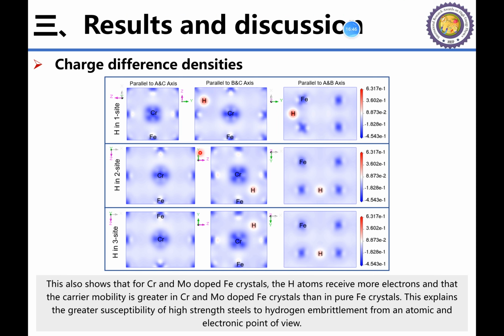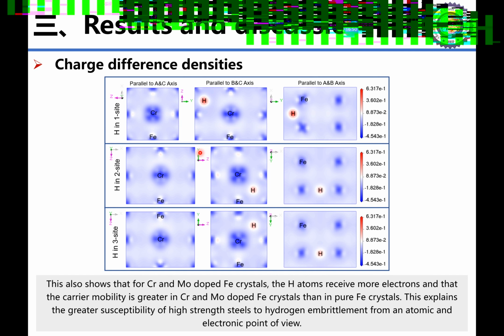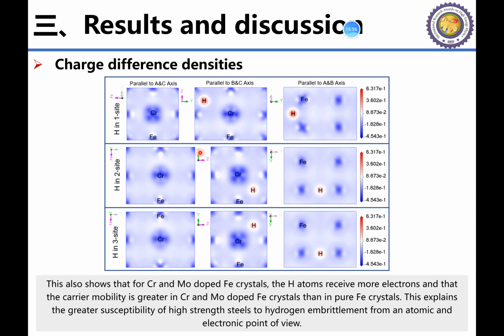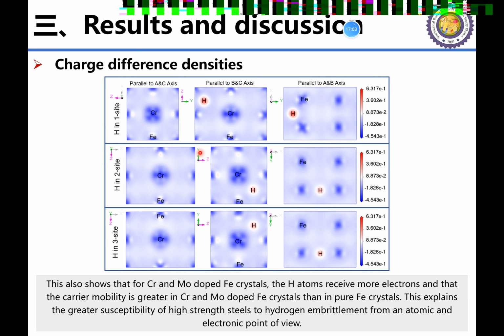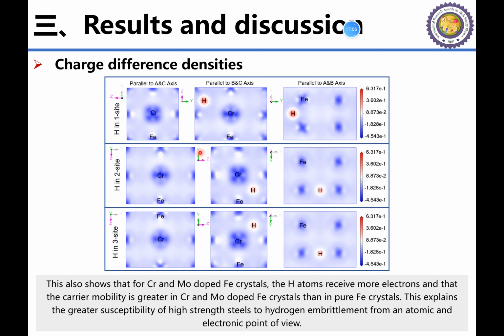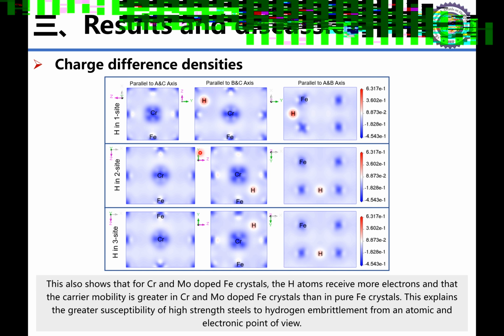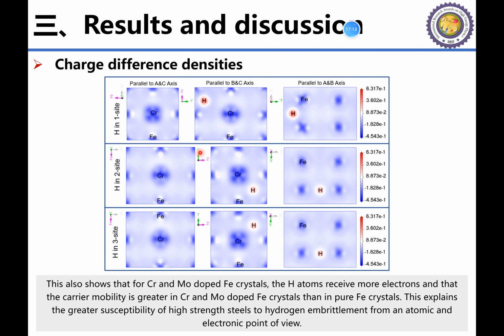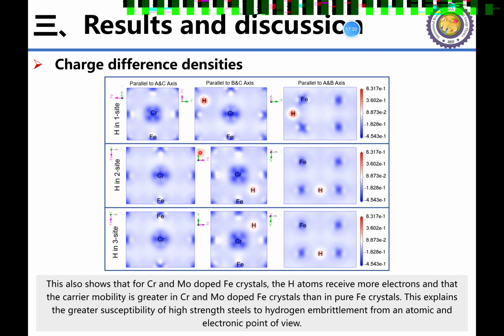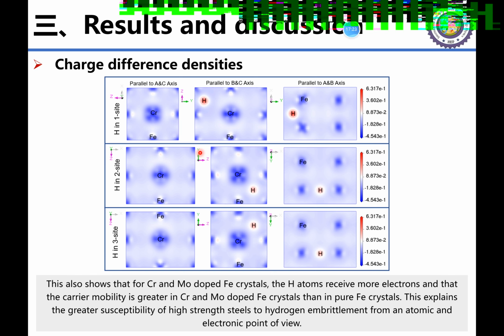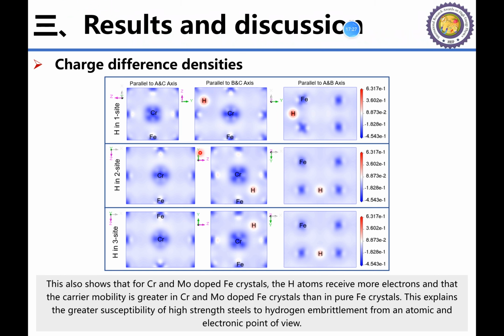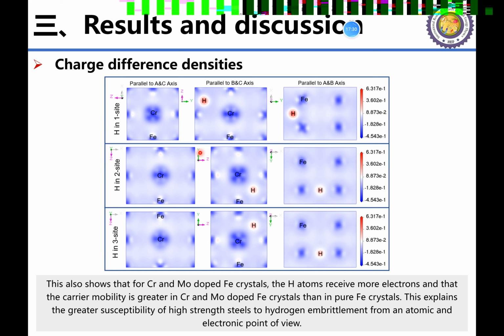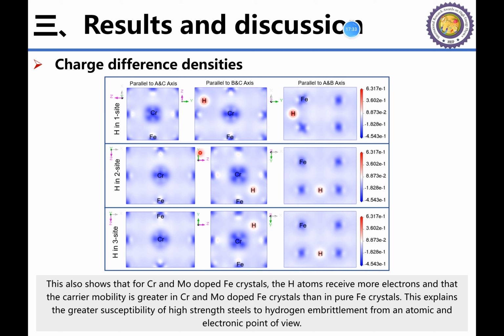And this difference is significant. This also shows that for chromium and molybdenum doped iron crystals, the hydrogen atoms receive more electrons, and that carrier mobility is greater in chromium and molybdenum doped iron crystals than in pure iron crystals. This explains the greater susceptibility of high strength steels to hydrogen embrittlement from atomic and electronic points of view.